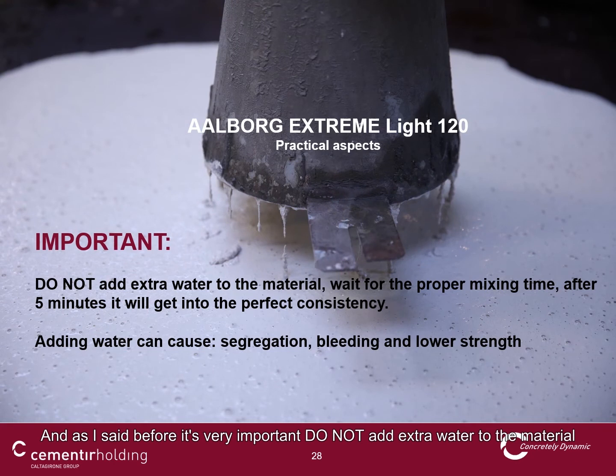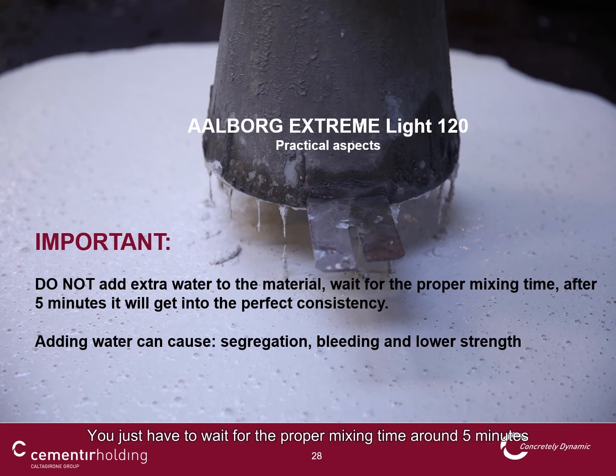And as I said before, it's very important, do not add extra water to the material. You just have to wait for the proper mixing time, around 5 minutes, and it will get perfect consistency. Adding extra water can cause segregation and bleeding, and of course lower strength. And if we have fibers, the problem will be even higher, because we will also have segregation of the fibers in the material.